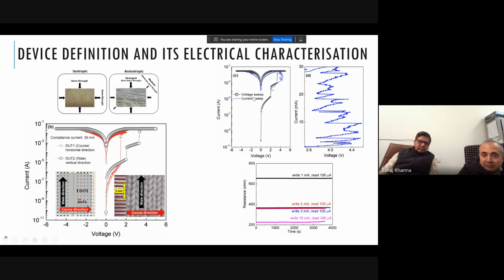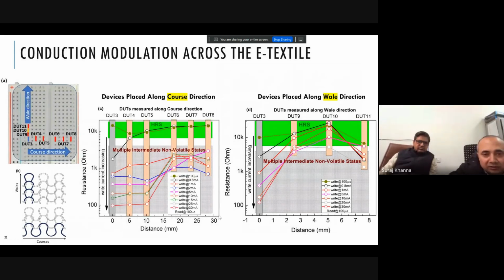We were able to apply the current in a very finely controlled manner. That's why we were able to see more states in between the first and the last resistance state of the device. So if you are applying 1 milliamp, the device may read something around 700 ohms, and then if you increase it to 2 milliamp, the resistance falls, and so on and so forth. If you go to 10 milliamp, the device resistance may go down to roughly 200 ohms. So as you apply a higher current, the resistance falls. Because the material is now in a fabric form, and this fabric is known to have high anisotropy, that's what we saw in the device testing also.